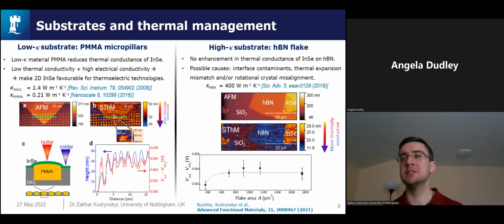In contrast to this, an enhancement of thermal conductance would naturally be expected from a material with high thermal conductivity, such as hexagonal boron nitride. However, our studies did not reveal any significant increase in thermal conductance compared to indium selenide on silicon dioxide. This unexpected result could potentially originate from thermal expansion mismatch and/or rotational crystal misalignment.